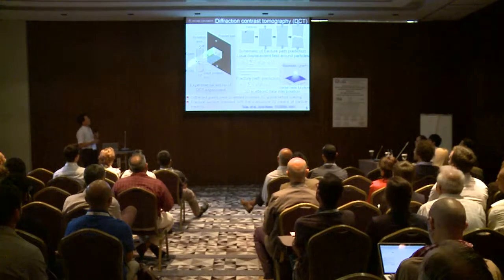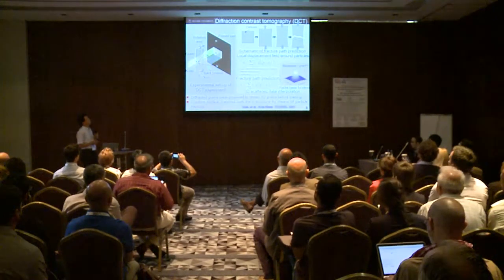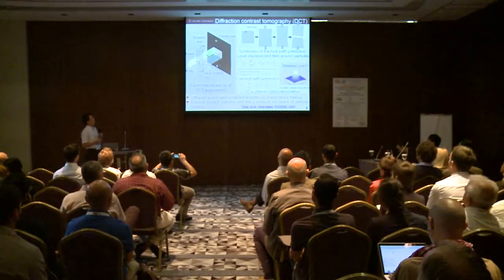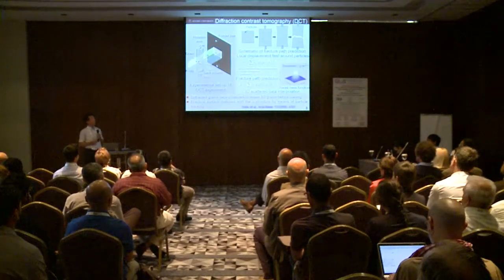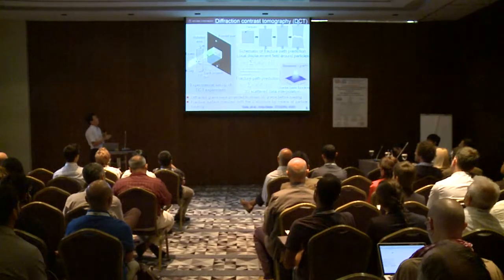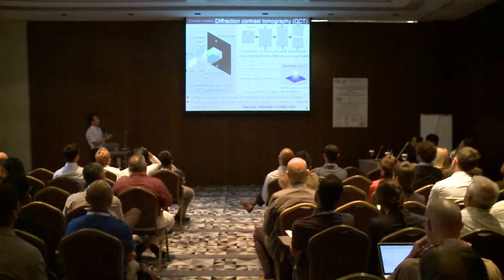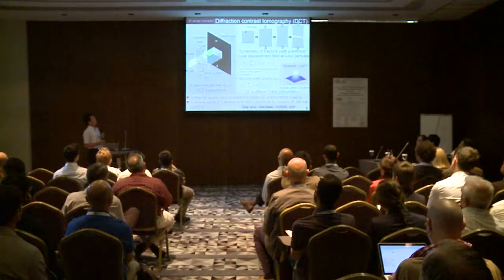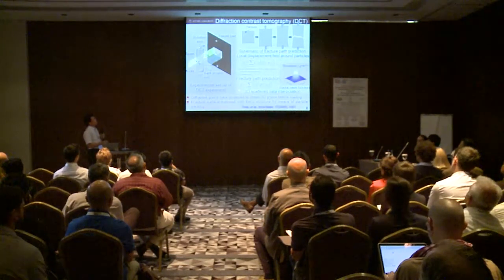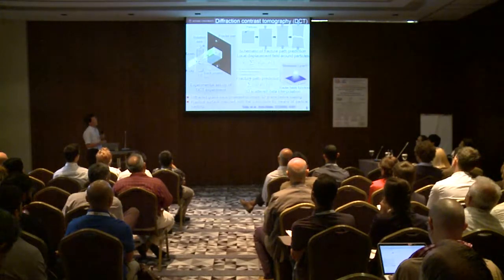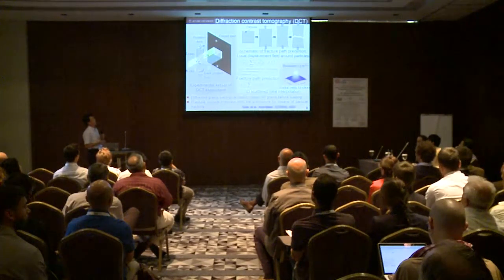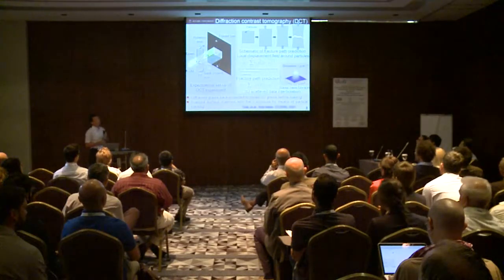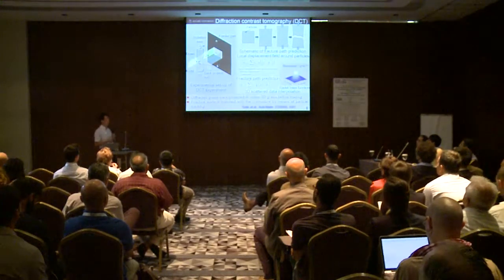And we also apply the diffraction contrast tomography technique to see the crystallographic structure of a material. But the problem is this technique is only applicable to the initial unloaded state. So we have the crystallographic structure at the initial unloaded state, which should be correlated with the fracture surface, because we have 30 to 50% plastic strain in between. In such a case, we use a 3D scattered data interpolation, and we don't go into the details of this technique this time, but fundamentally, we obtain the local displacement field on the basis of the physical displacement of all the 100,000 particles.